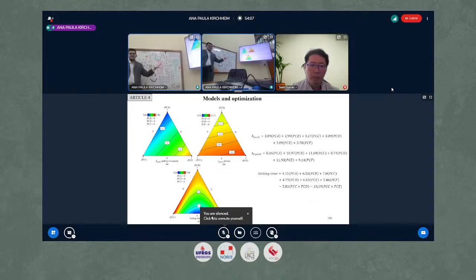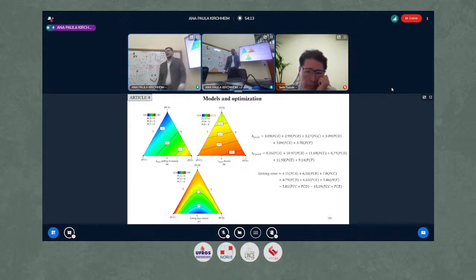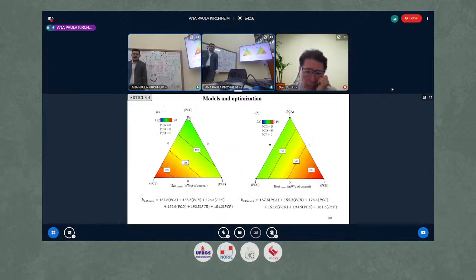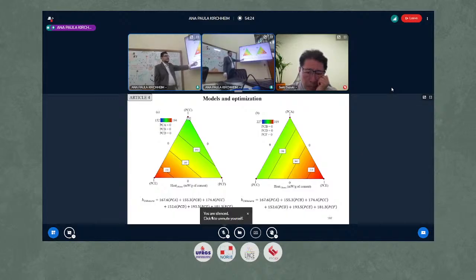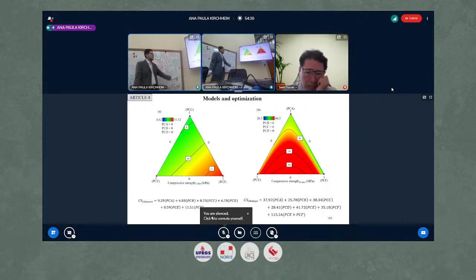So I ran some models here to try to predict the heat peak and the setting time with our Portland clinkers. I will pass those to the next section, but here we see some models to predict the heat release after 1 day with the 6 clinkers that we analyzed. And here the output is compressive strength at 24 and 28 days. In general, we obtain good models with very good statistical results, showing that we can use this statistical mixture design to optimize our cement if we have different clinkers.